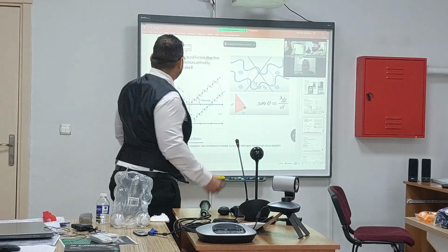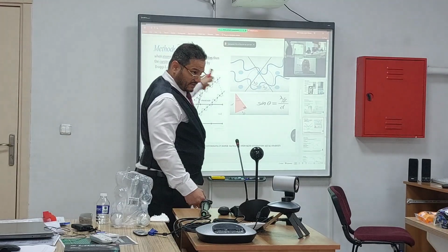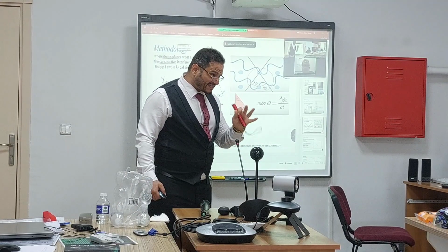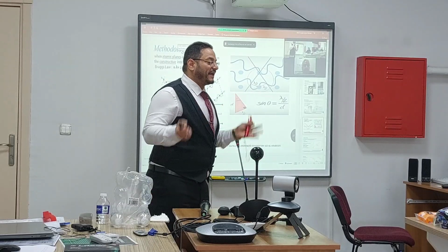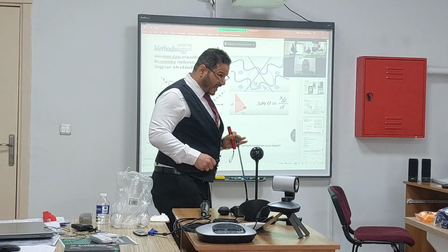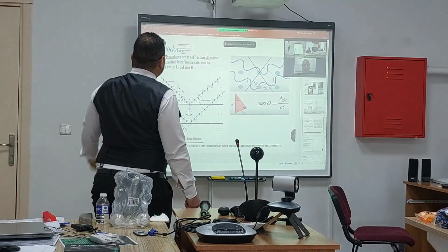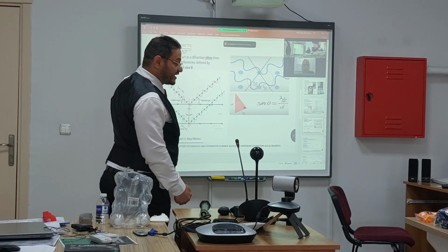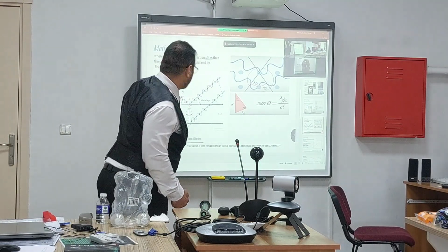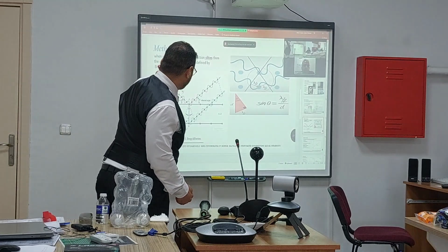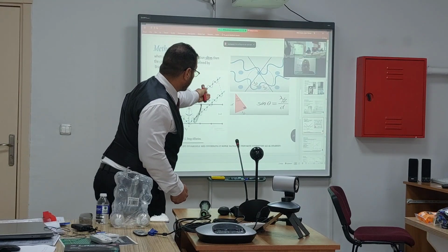All right. The atomic planes here are very important. They act like slits, because that's how I have peaks, okay? The atomic planes act as slits. The constructive interference is defined by Bragg's law, lambda equals 2d sine theta. Here, wave number 1, wave number 2.